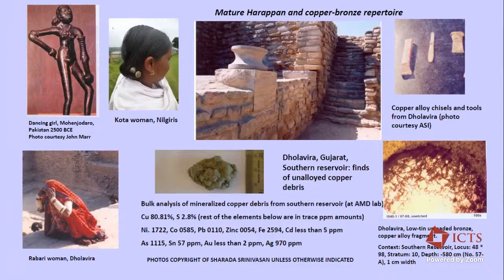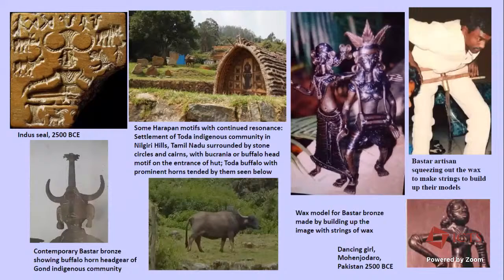And then you also find that in Dholavira, there is an analyzed copper alloy fragment, which has what we typically call the composition of low tin bronze. That is not a very high content of tin, certainly less than about 10%. And it is also unalloyed with lead here. So this is what we call binary bronze, where it is just a copper tin alloy that's been used. But you also find that this is similar to what was observed for the dancing girl and so on, that those were low tin bronzes.